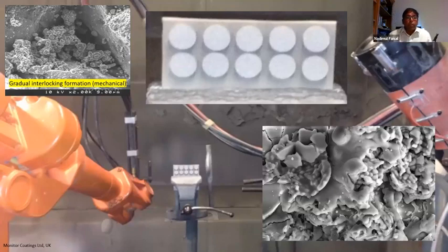Most of the time, it depends on the technique you are using, and it forms a mechanical interlock with the rough surface. And with the control on the process parameters, like what distance the gun should be, what should be the velocity, what material, and so on. There are about 6-7 types of process parameters which can be looked into to design the coating or electrode you want to develop. So you can control the porosity, the thickness, the roughness. So a number of things can be done from this technique.